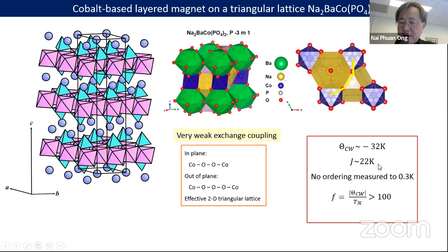Yeah, so the estimated exchange, there's some debate within the group about the best way to estimate that, but it looks like it's about 30 Kelvin. So it's a fairly small exchange and a small Curie-Weiss temperature. So what was the other question? I missed that. Oh, I think that covered it. Yeah, so the frustration ratio, so this is the Ramirez ratio, right? It's about 100. So this is a fairly frustrated system. Right.